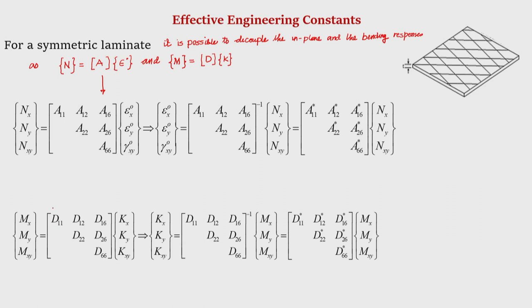N x is equal to A into epsilon naught. Nx, Ny, Nxy are the in-plane force resultants per unit length, epsilon x naught, epsilon y naught, gamma xy naught are the in-plane mid-surface strains. Therefore, if we take inverse of this A matrix, we can write the mid-surface strains in terms of the force resultants, and suppose the elements of the inverse of A are denoted by star. Therefore, this A11 star, A12 star, these are the elements of the A inverse matrix. This is nothing but A inverse. Okay. So, this is our equation number 1.